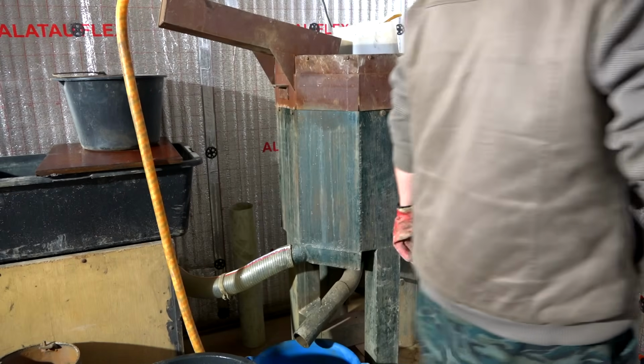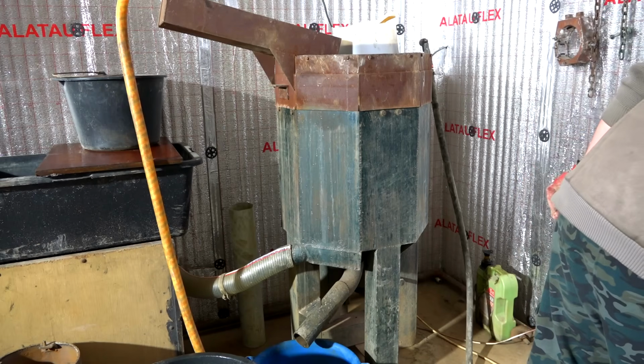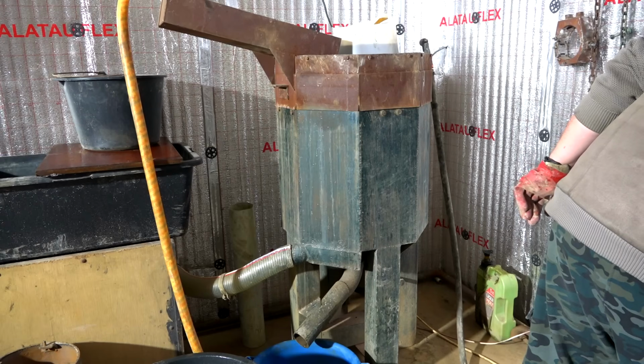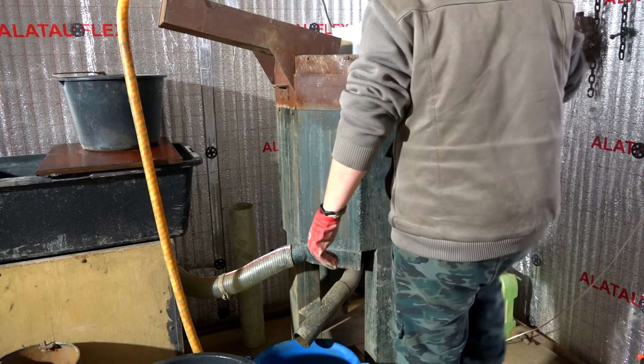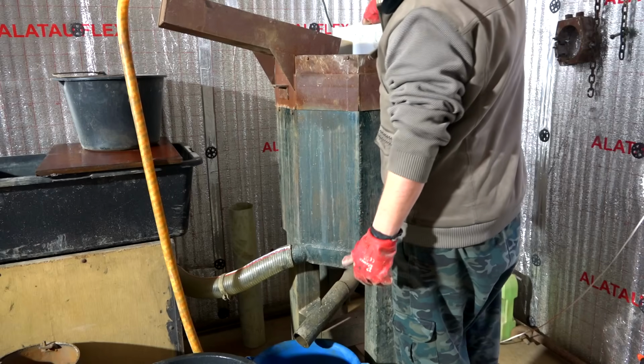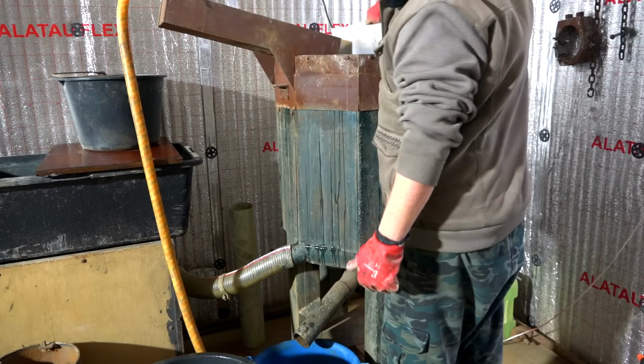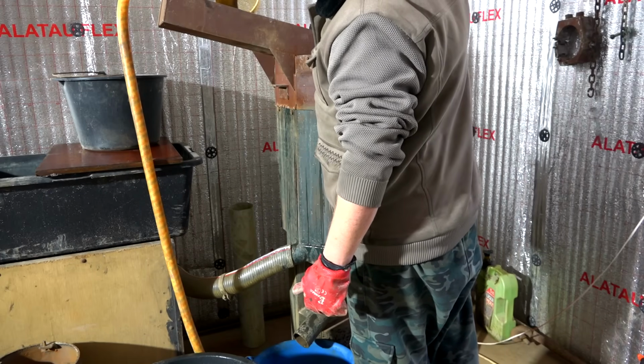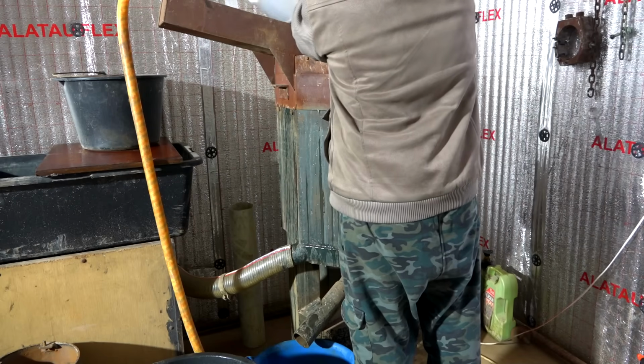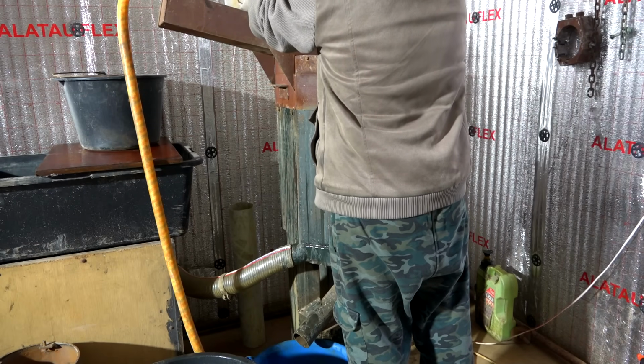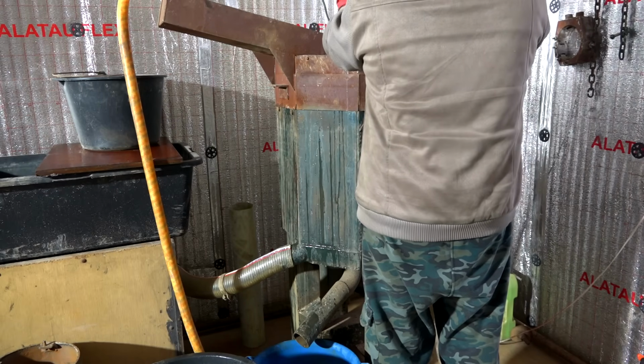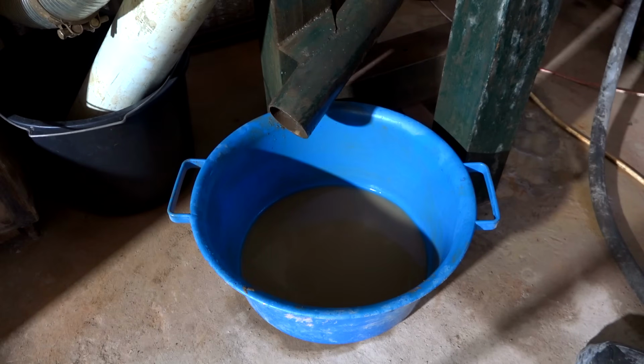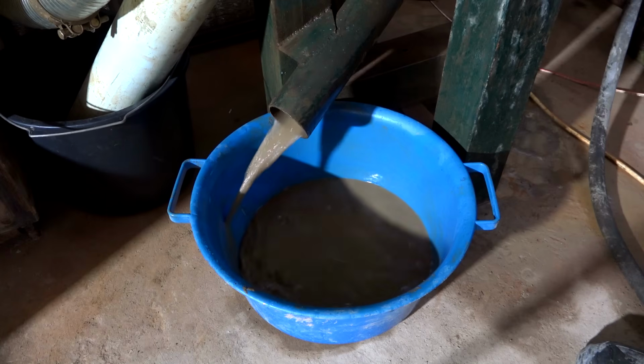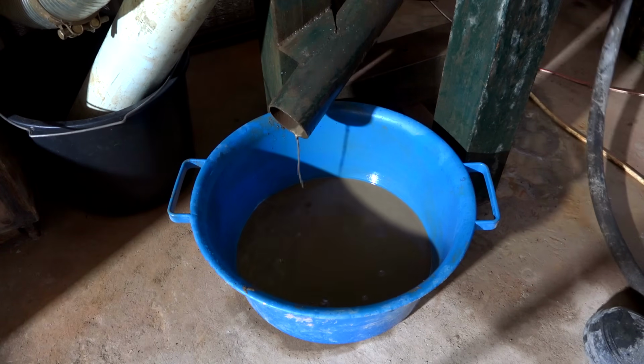This way, from 100 kilograms of pulp, I'll get the most valuable part, a concentrate containing gold. After 15 minutes, I'll have valuable concentrate, approximately 3 kilograms. Each wash can yield 1 gram or more of gold, depending solely on the ore. But this concentrate will require additional processing to extract all the gold.